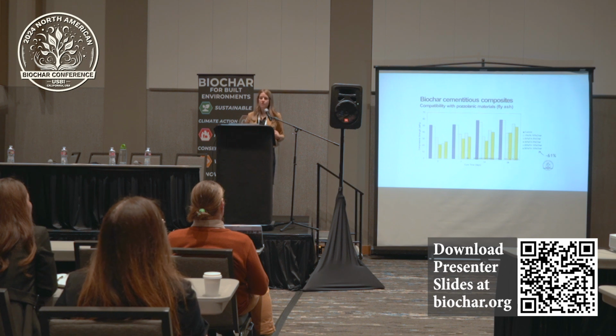So it allows us to potentially replace more of the cement with fly ash by adding some additional biochar, which is carbon negative. So it's a win-win in terms of reducing carbon footprint. And you'll see here that this mix shown with the dark yellow and the dotted, we're already at a 61% carbon footprint offset. So that's not our goal.